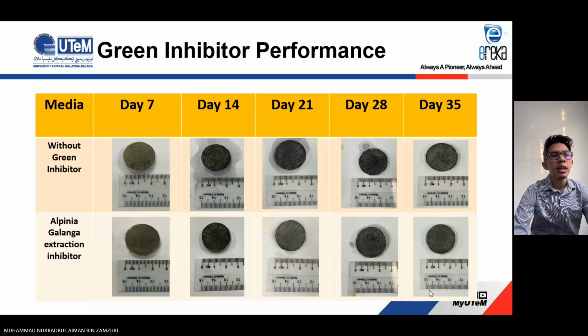For the green inhibitor performance, the table shows the results of carbon steel samples that have been immersed in 0.5 molar hydrochloric acid solution with and without inhibitor at day 7, day 14, day 21, day 28 and day 35.